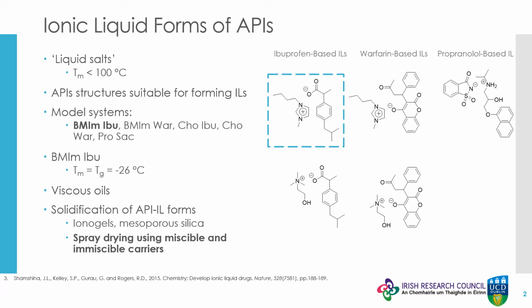Methods for solidifying API-ILs that have been previously reported include immobilizing them in ionogels or mesoporous silica. However, as gels cannot be readily incorporated into existing formulation process streams, and the silica approach struggles to achieve complete desorption from the solid carrier, a more practical means of solidifying API-ILs remains to be found before they can be routinely incorporated into solid dosage forms.